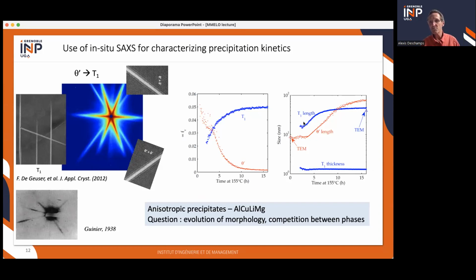And the other particles grow in size, and the respective volume fractions cross each other because you have theta prime, which disappears to the profit of T1. So here, in situ gives you really the kinetics of the transition between two phases, one metastable and one stable.